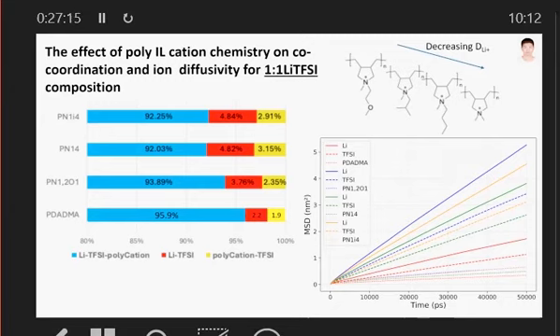And if we look over here, we see some really interesting observations. The red is the polyDADMA, the one that we know and love so far. The blue is the material containing ether oxygen. So there's a huge difference. And the bold lines versus the dashed lines: the bold lines are the lithium, and the dashed lines are the anion. So two things. First of all, in all cases, the lithium ion is more diffusive than the anion, which is what we've seen both experimentally in the previous systems and also from the MD. But the trend is interesting. Here the ether oxygen gives you the best diffusivity compared to the polyDADMA, and then the isobutyl and this long chain butyl. So that was the trend from the MD simulation.